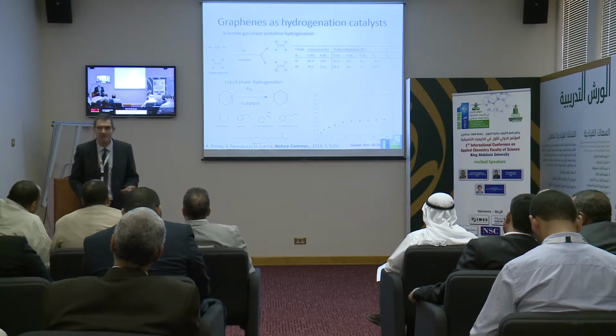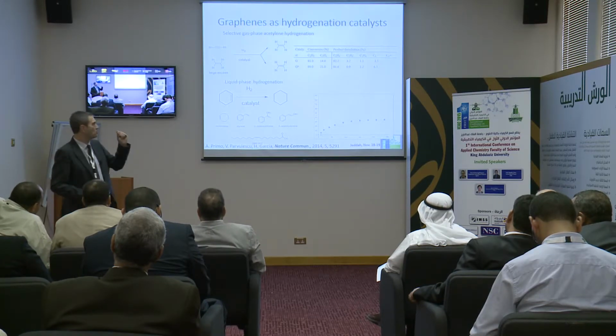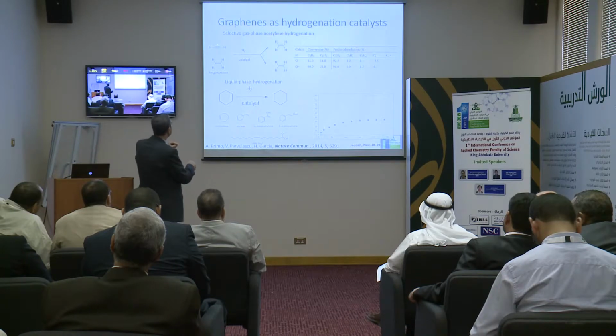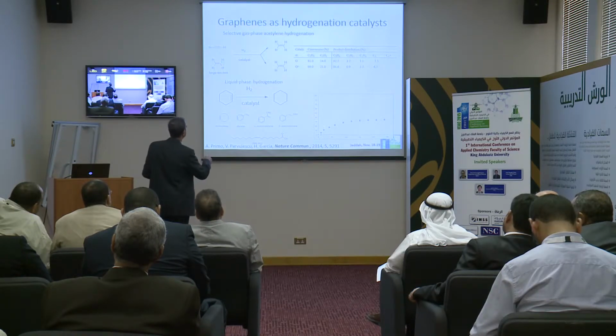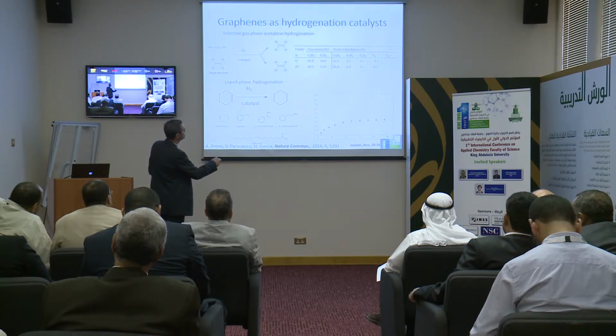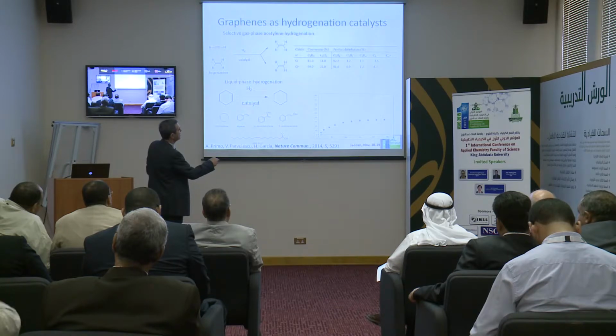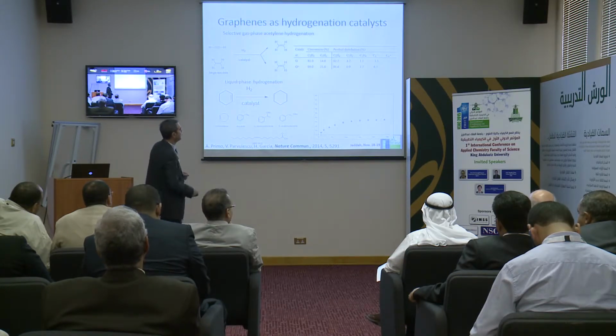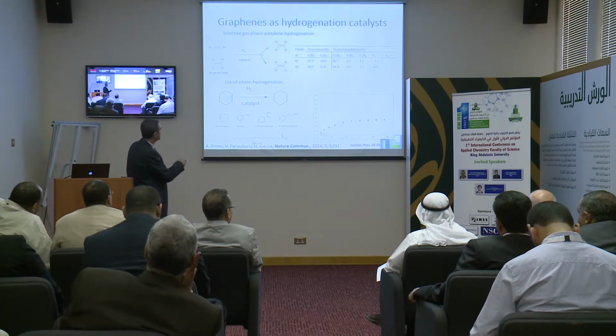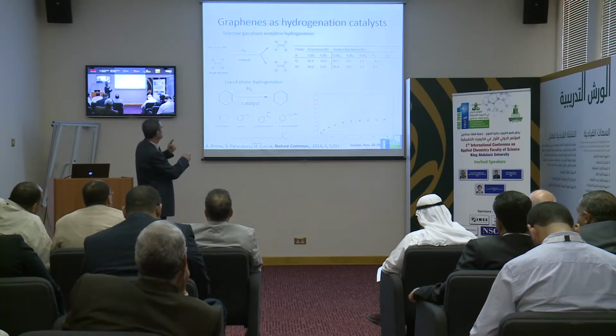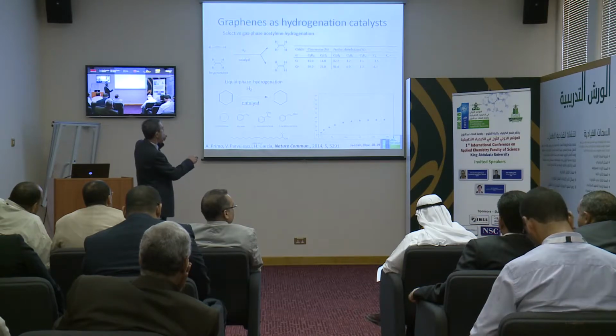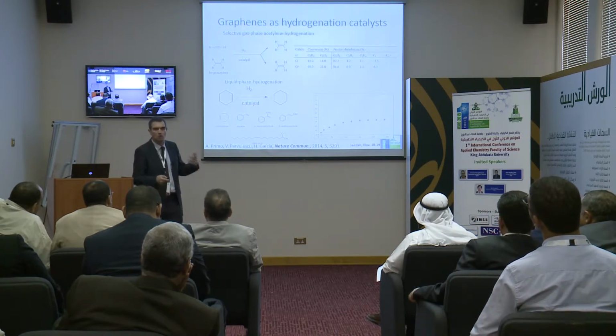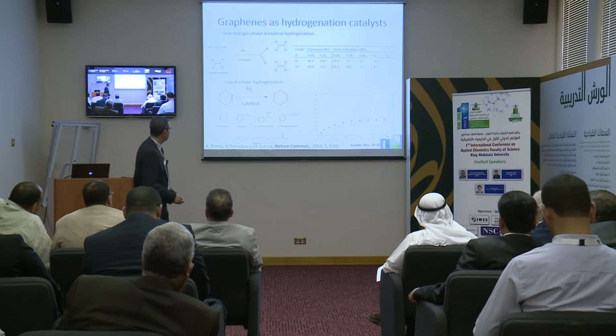And one of the possibilities would be just the selective hydrogenation of acetylene in the presence of a very large excess of ethylene. And just using graphene, what we observe is that we can hydrogenate acetylene 81% and only promoting the hydrogenation of a very small amount of ethylene. So this is a very important target, because in that way, if we are able to hydrogenate only this compound to this compound, then there is no point in purification because we have already purified.